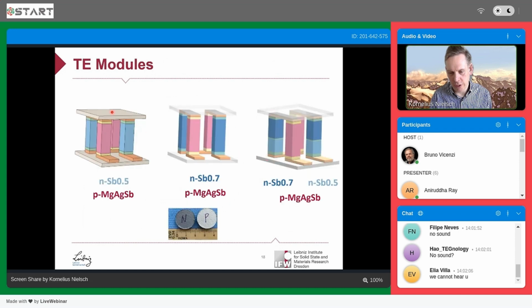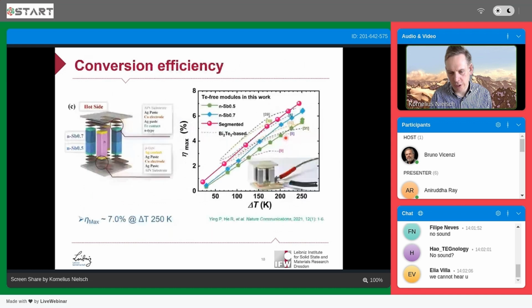What I will show in the first study is that we used different compositions as a segment design to optimize these thermoelectric modules. We have a composition of 0.5 antimony, then 0.7 antimony, and we combine both compositions in a segmented manner to obtain an even higher efficiency.